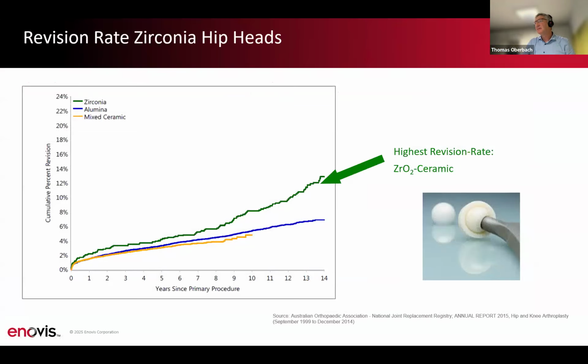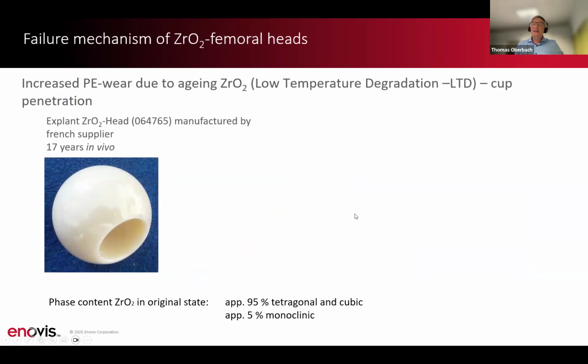And this is an overview from the Australian registry from 2015, 10 years old. The zirconia heads showed the highest revision rate in comparison with hip implants with an alumina head or also a mixed ceramic head. And the reason for this higher revision rate, after 7 to 8 years you see the revision rate increases, was that the zirconia ceramic showed the LTD, the low temperature degradation. And this led to a penetration of the head in the cup.